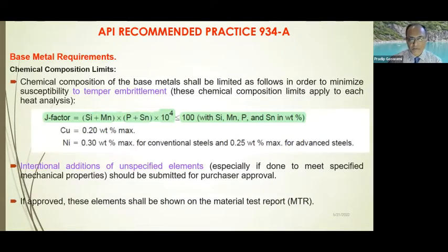Base material for these grades of steel has to be absolutely precise and made to the, I would say, the best engineering practice. And typically, all these materials which are used in this application are subject to a process called temper embrittlement when they're exposed to the temperature range of 450 degrees C or so, right? Or somewhere in that range. And basically, chrome moly steels are very well known for temper embrittlement in that particular range.